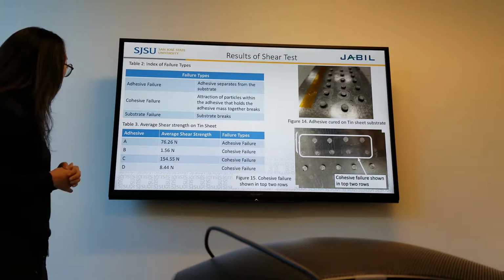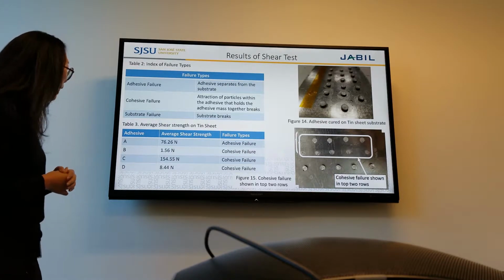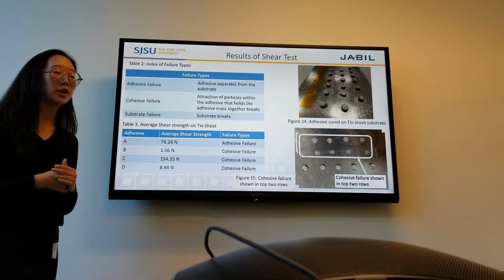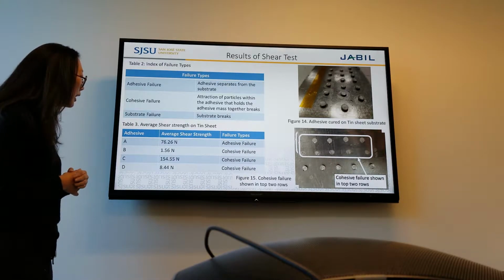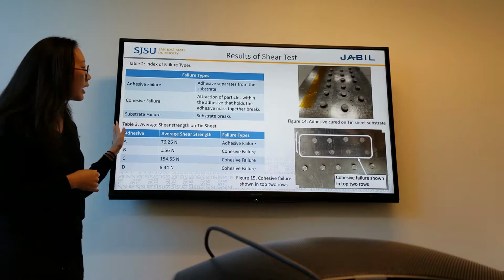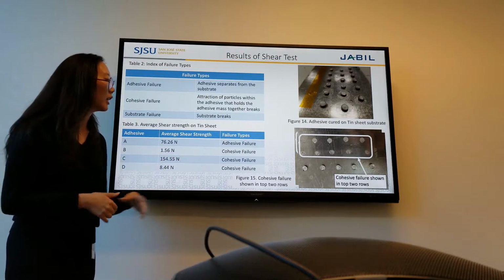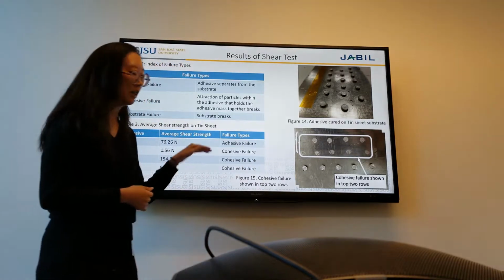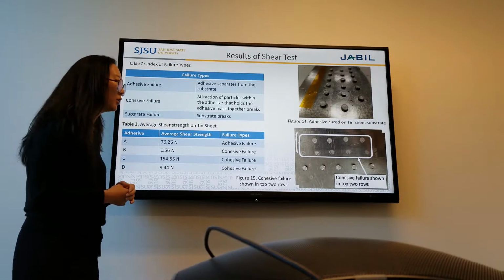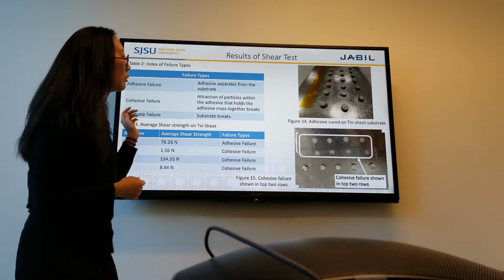For the average shear strength, A and C displayed really high shear strength compared to B and D. And all of them except for A displayed a cohesive failure. And over here you can see what a cohesive failure looks like. You still see a thin layer of the adhesive still attached to the substrate. And this is what the adhesives look like when they're cured on the tin sheet.